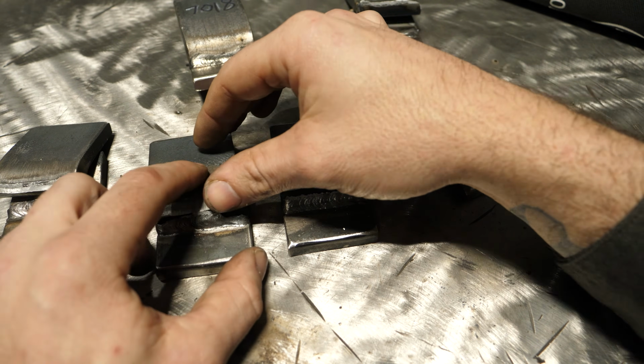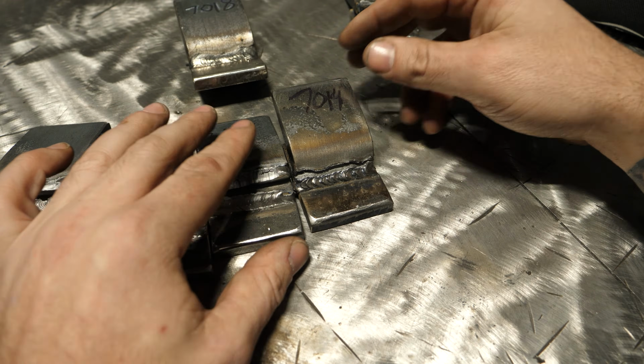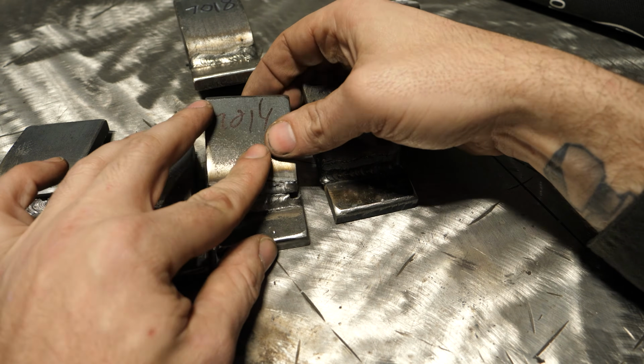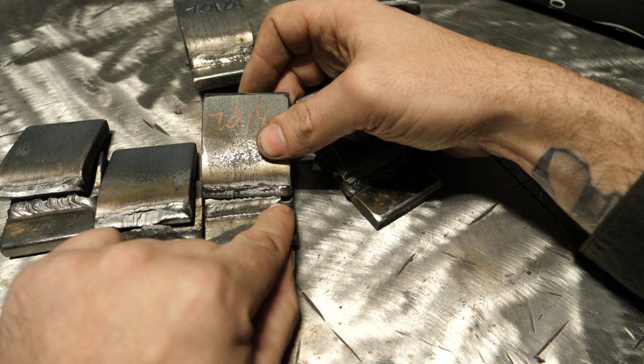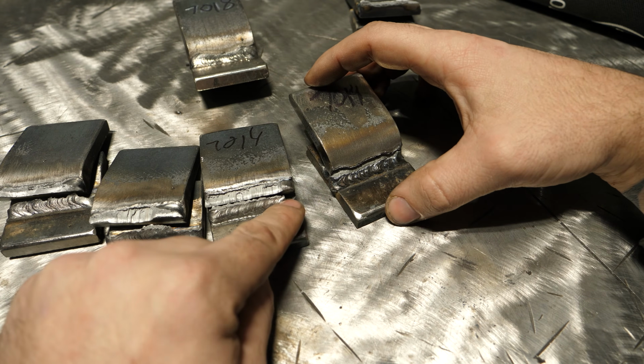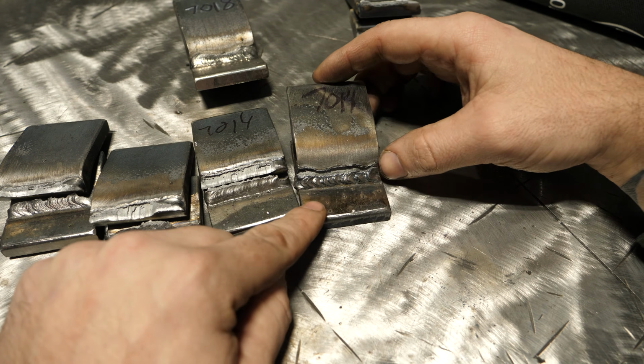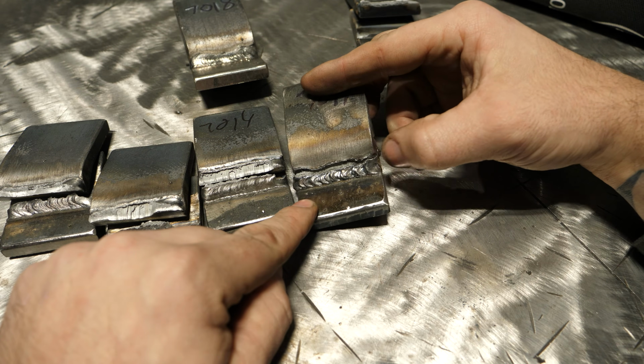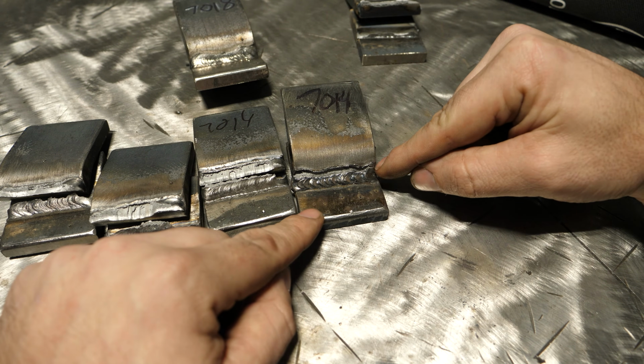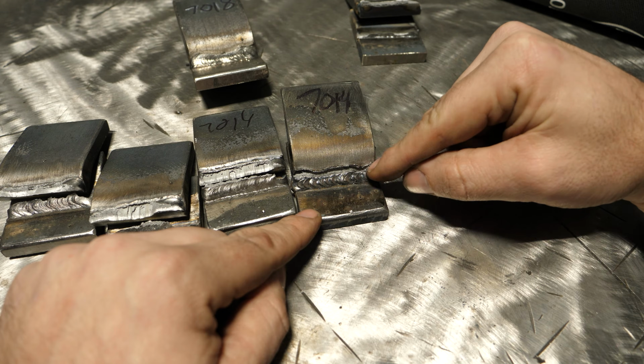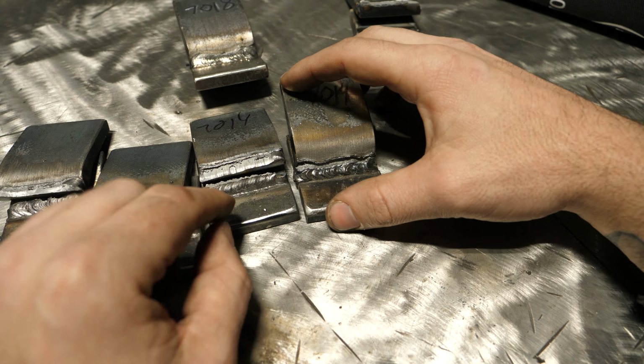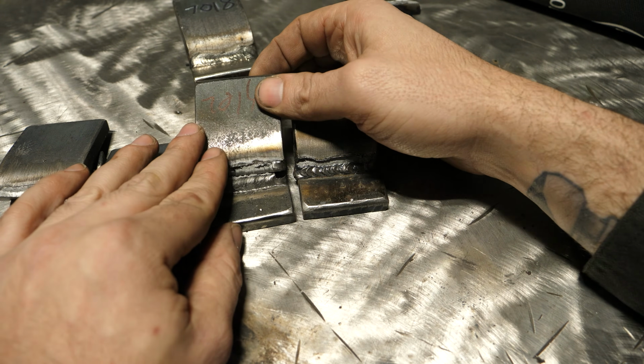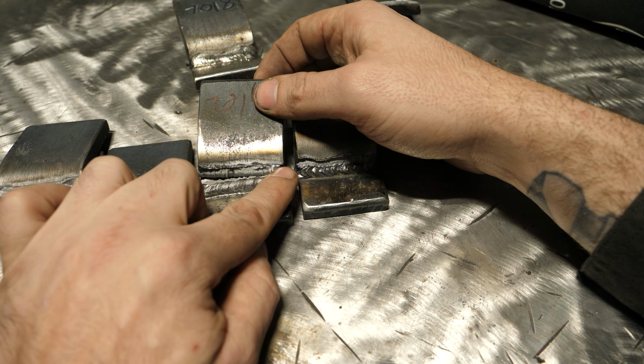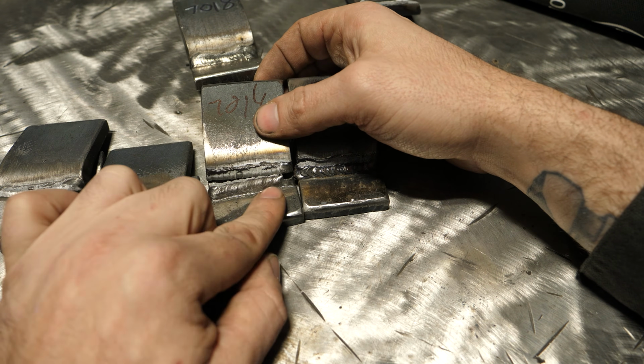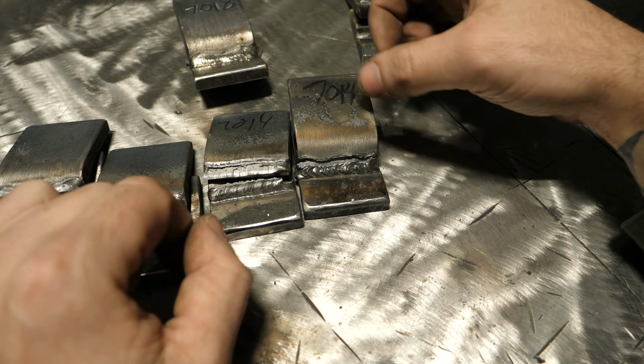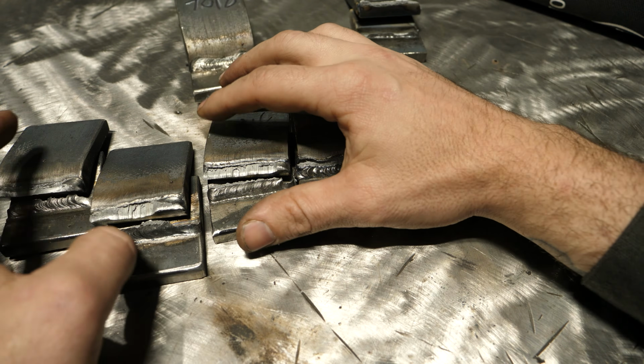Pretty interesting results. Now, the 7014 tends to tear right at the toe, and I don't leave too much of a fisheye there, but there is a little bit of one. This one was filled in far better, and all that happens is the crack starts and it breaks up top of it rather than down here and then up. I don't honestly think it would make much of a difference if that was completely filled in or overfilled. It's still going to break on the top toe line because of how this is stressed.